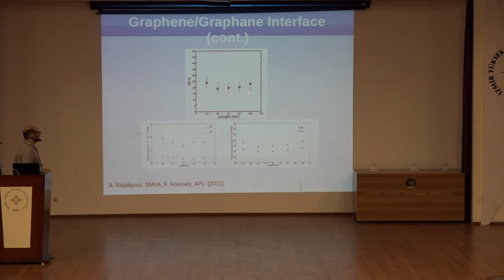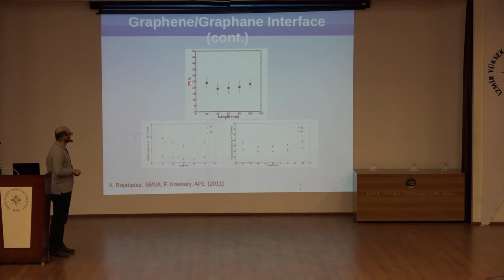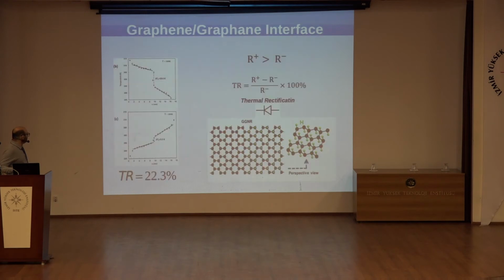Here is what we have obtained for a considerable length of the system. It is possible to get about 25% of thermal rectification, but the direction is this way, from hydrogenated to the pristine one. There is better heat transfer than in the opposite direction.